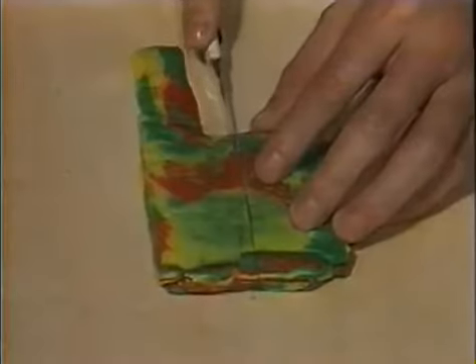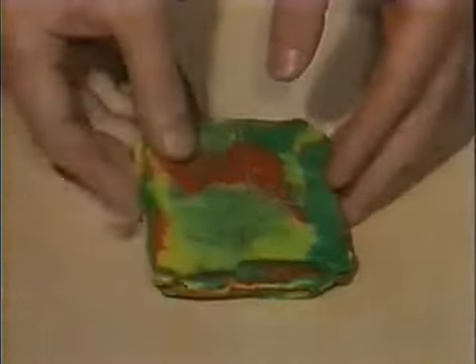With every repeat of orikaeshi, the number of layers doubles. After the 10th time, the steel consists of 1,024 layers or more. After polishing of the final blade, these different layers show up in an exquisite surface pattern known as the sword's jihada. In the folding lies the secret to the sword's combination of strength and beauty.